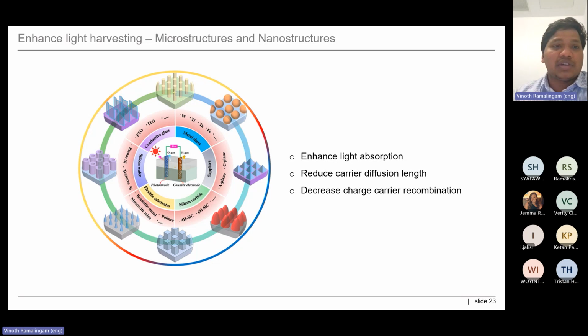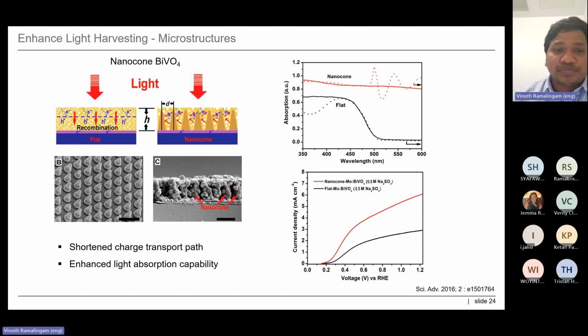So here is an example of enhancing light harvesting ability through microstructure and nanostructure. You have different nanostructures and microstructures, for example, from bulk to different structures like nanotubes, nanorods, nanoparticles, nanospheres, that can really help to improve the light absorption ability of the photoelectrode. Basically, that will help you to reduce or shorten the carrier diffusion length so that you can avoid charge carrier recombination. That will help you to improve the charge carrier separation and achieve better PEC performance.